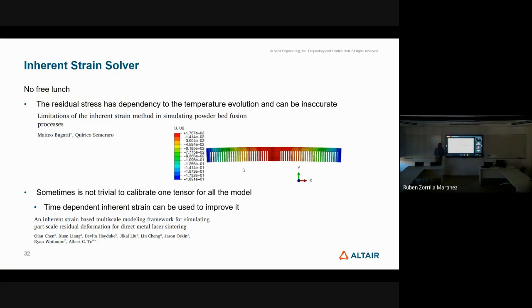And sometimes it's not very easy to have only one inherent strain for all your pieces. Basically, depending on your temperature and temperature gradient in space, not in time, you may get different results for the inherent strain. In fact, there are people who are suggesting using different inherent strains depending on the temperature.